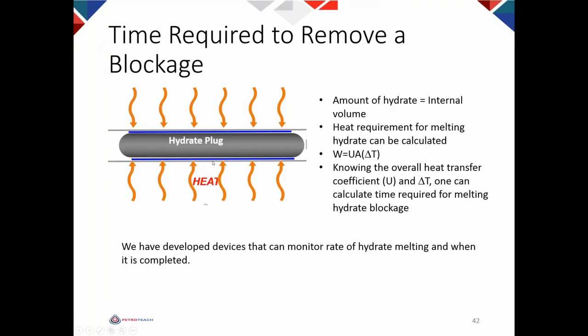Time required for removing a blockage. How much time do we need to remove a hydrate blockage? So basically, imagine we have hydrate here, a unit length of the pipeline. You can calculate the amount of hydrate by knowing the internal diameter of the pipeline. So knowing the internal diameter, we can calculate the internal volume and the amount of hydrate. If we know the type of gas or gas mixture, we can calculate the heat requirement for hydrate melting via dissociation. So this is the heat requirement for melting hydrate.